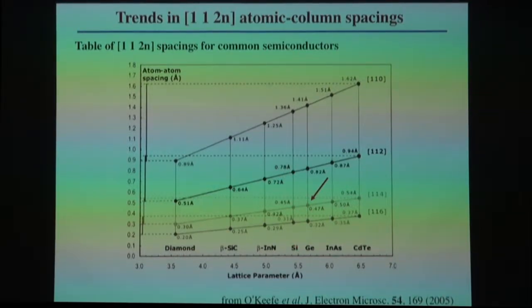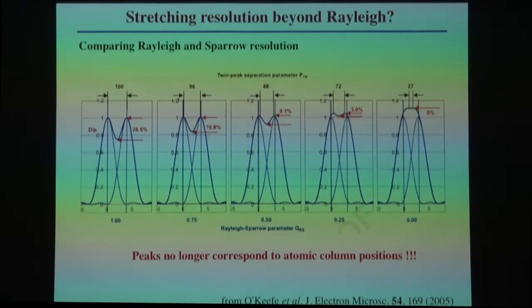There was a paper published about two weeks ago in APL, and I haven't got the image to share with you, but it was showing 0.43 angstroms separation of gallium atoms in gallium nitride. So this is where we are these days. Do we know the sample? Yes. If we know the sample and the projection, we know how far apart the atoms are, so then we could use a sort of Rayleigh criterion to say, yes, we can see this particular spacing in the image.